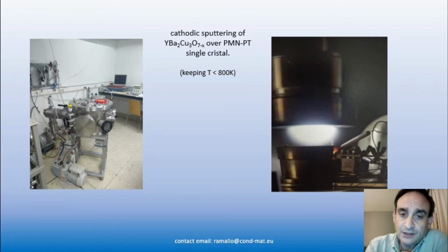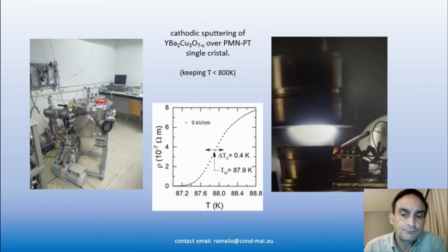One has to take into account that one needs a growing method that does not exceed 800 K, because otherwise there is a phase transition in this type of substrates. But if one takes that into account, one obtains films with very sharp transitions, quite standard when you do not apply the piezo voltage.